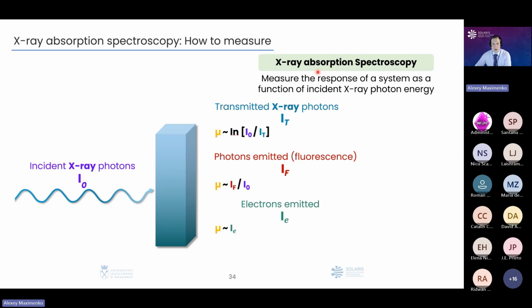And in this case, when we make X-ray absorption spectroscopy measurements, we could use a standard Lambert-Beer law. We investigate the intensity of the X-rays before the sample and the intensity of transmitted radiation, and using it, we could investigate what is the absorption coefficient value. If we measure fluorescence, which is actually excited by the radiation which we radiate our sample, we could also calculate the absorption coefficient, and also we could measure this current, as I told you, which is emitted by the sample under the X-rays.